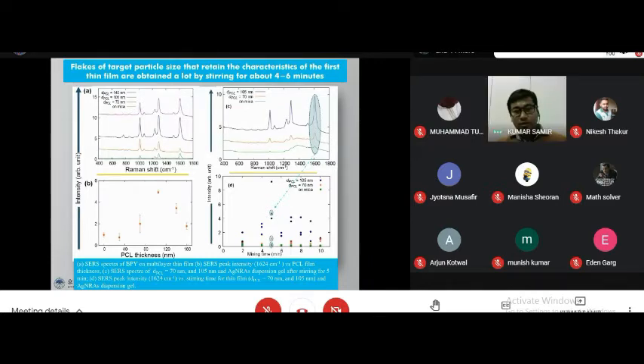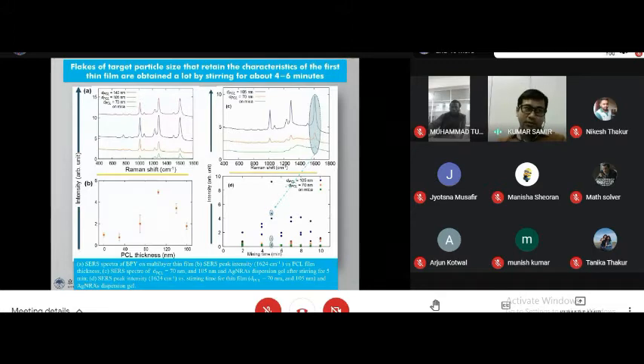Next, we wanted to get the maximum enhancement factor, and for that we optimized the PCL thickness. We found that for 5 minutes of mixing, and with a PCL, the phase control layer, of 105 nanometers, it gives the maximum SERS enhancement. So we utilize this sample for our sensing application.